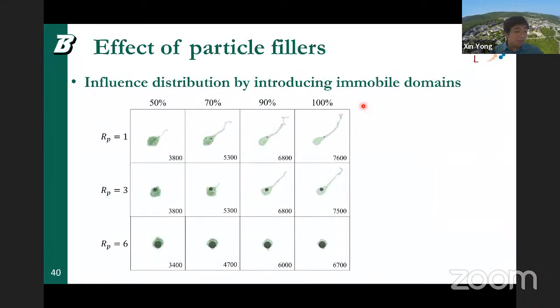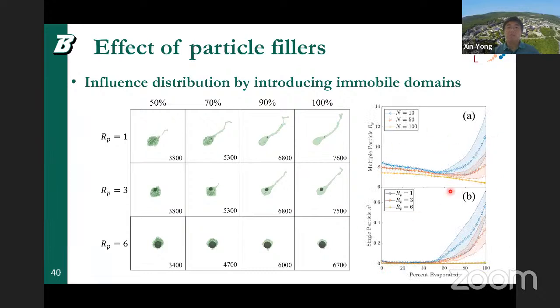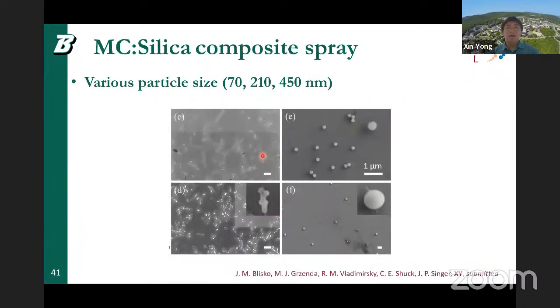And so I've pretty much used up my time, so I'm going to quickly flash through some of these additional new developments that we're doing here. We're further looking into the influence of particle fillers. Here we're adding in particles of different sizes to the droplet and trying to observe their influence on the morphological evolution. It's very clear that when the particle is large, it can arrest and suppress the deformation. And this can be characterized by the relative shape anisotropy and the radius of gyration.